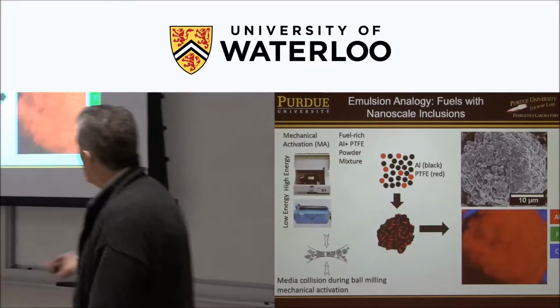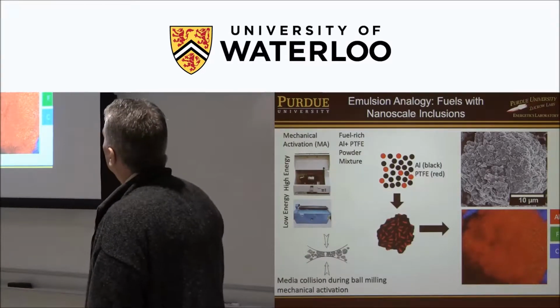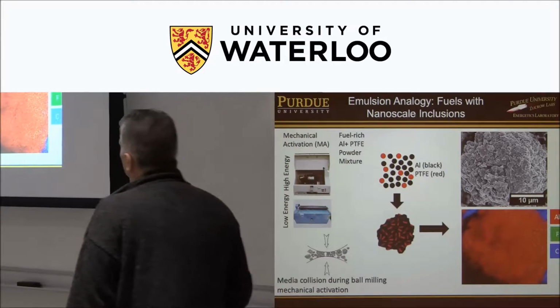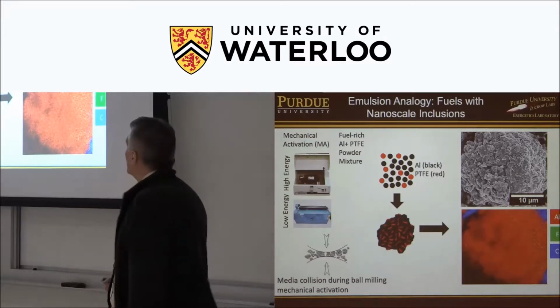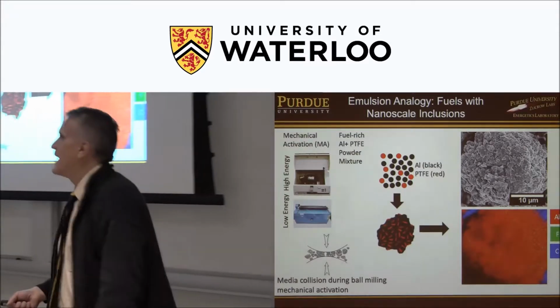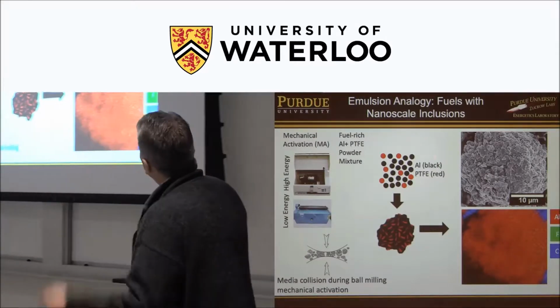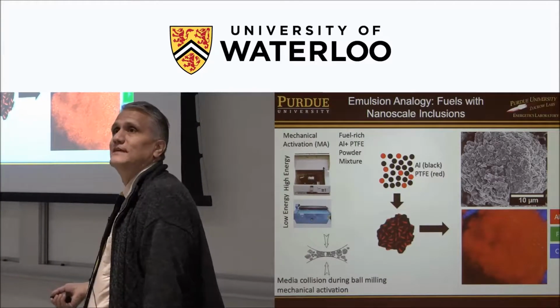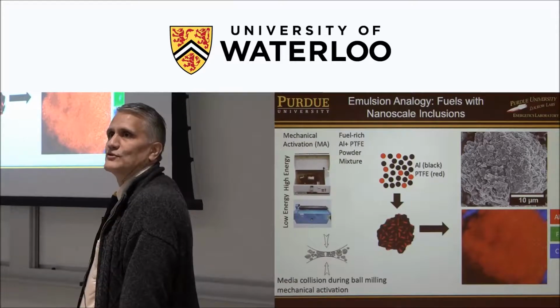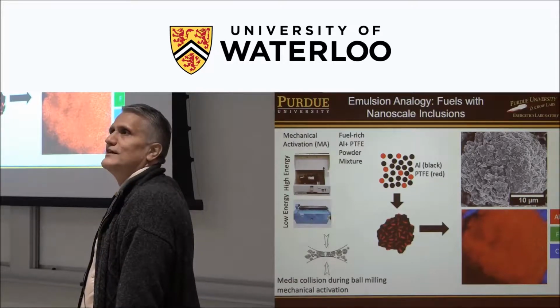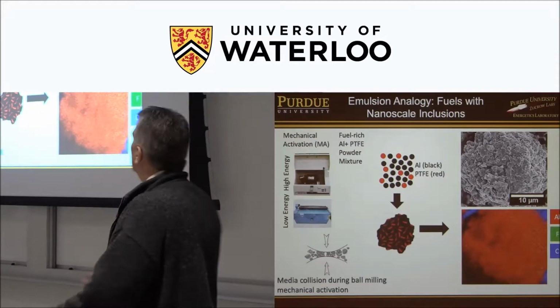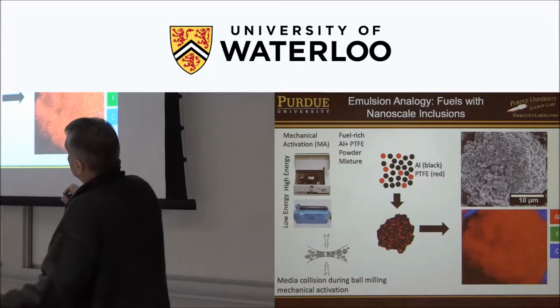And this is just a schematic of how we, in a very top-down method, almost like a sledgehammer approach, make nano-featured materials. We put aluminum and, in this case, Teflon. And what did I say about fluoropolymers? To me, those are oxidizers. So this is an interesting composite particle in that it has some oxygen, or in this case, fluorine, which is an oxidizer for the aluminum.